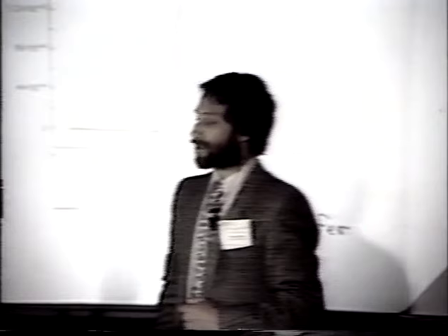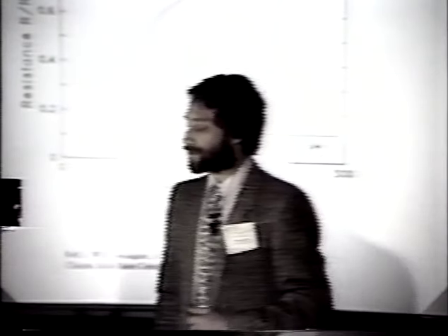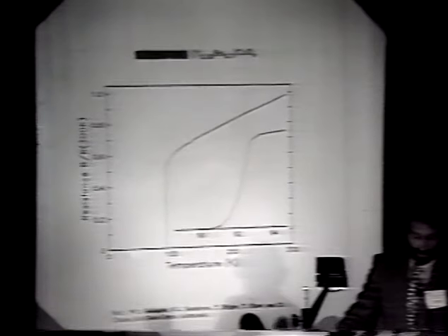I'll start briefly by just showing standard transitions in resistance versus temperature with the lanthanum-strontium compound and with the yttrium-barium compound, observing nice sharp TCs in the right places, and most recently with a 400 nanometer thick thin film, which also shows a very nice transition with an onset at 97K.